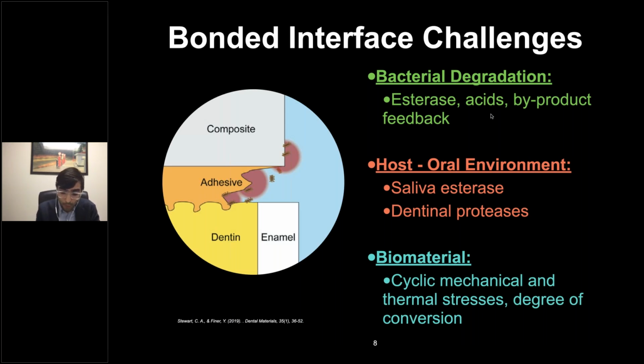And more than that, these esterases actually give positive virulence factors for the bacteria, meaning they use this degradation as a way to feed themselves and actually upregulate. So they become more active and increase their production level, which leads them to produce more acid and degrade even more of the restoration. That's a quite big enemy that these restorations have. That's why we're trying to make new adhesives and new composites to prevent bacterial degradation of these materials.